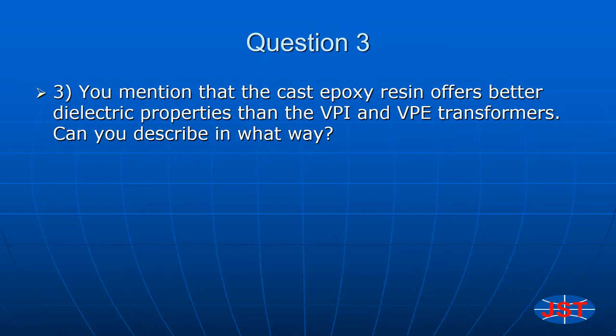Basically, let me stick with PD first. With the cast, because of the pressures you're able to realize in the vacuum casting chambers, you're able to get the epoxy to absorb into the crepe paper that's used for covering the wire when you wind these coils, and you're able to get a casting that's void free. There's nowhere anything else gets trapped between those windings, where it's a bit more difficult to achieve with VPI. And so the discharge you see is basically with the internal windings. There's a lot less discharge by nature of the structure of cast epoxy resin transformers than there is with VPI.